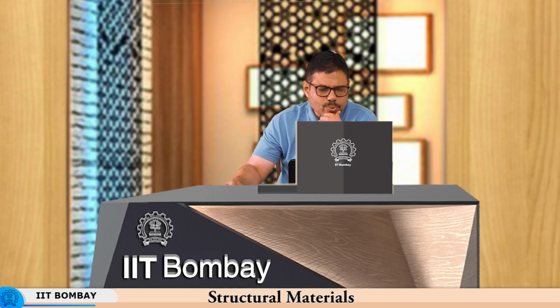So, again, both these behaviors are very similar to creep type of behavior, because viscous flow is again a part of the creep deformation. Creep deformation does involve viscous effects. And then when you talk about rubbery, it is typical of elastomers or rubbers and thermoplastics at temperatures above viscoelastic range. So, if the temperature is above viscoelastic range, then this is the kind of deformation you see over here.